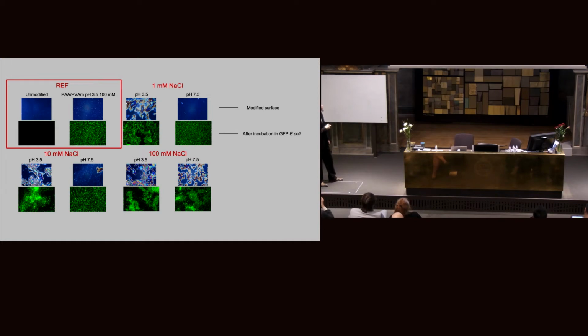First, we can see that at lower pH, the CNF samples tend to form these aggregates and island-shaped structures on the surface. And with increasing salt concentrations, we can see that the aggregates become bigger and larger.